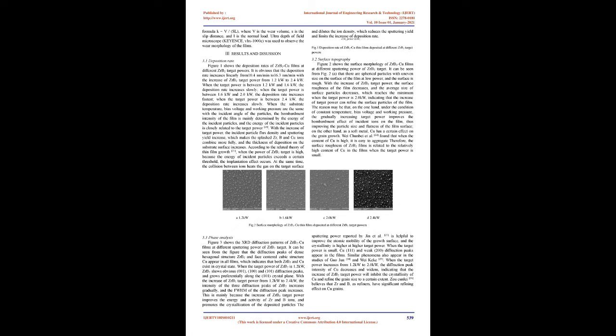2.2 Structure characterization and mechanical properties test. 1. X-ray diffraction, XRD, was used to analyze the phase composition of the films. The monochromatic K-alpha ray, wavelength 0.154 nm, from a Cu target was used to radiate. The power was 40 kV x 40 mA. The scanning range of diffraction angle, 2 theta, was 20 degrees to 80 degrees and the step width was 0.02. The counting time of each step was 0.2 s. The surface and cross-section morphology of ZrB2-Cu films were observed by S4800 field emission scanning electron microscope, SEM.